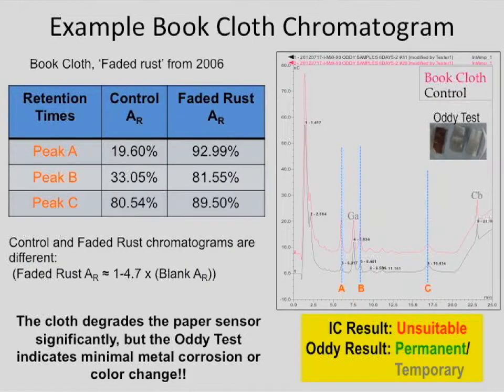In this case, looking at a book cloth, I think this is probably the one I showed you earlier, where these peaks get much larger, whereas C doesn't show any change. But much like the Oddy test, if any of the chromatogram peaks are larger, or if one of the coupons is considered unsuitable, or any of the peaks are larger than the control peaks, then we'd say the whole sample is unsuitable or temporary.